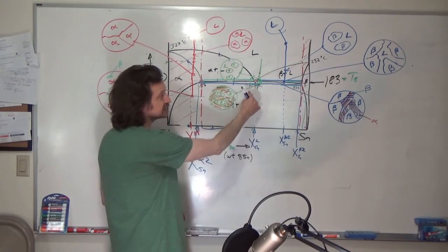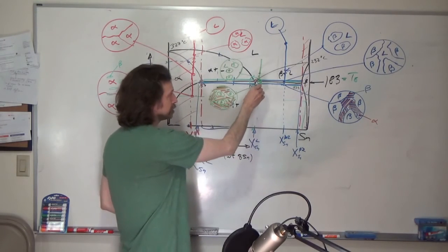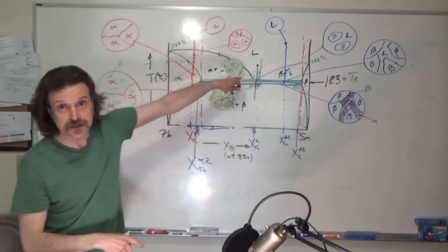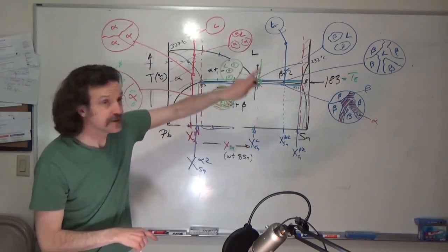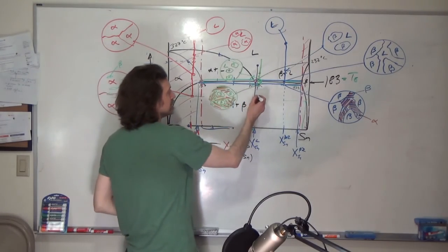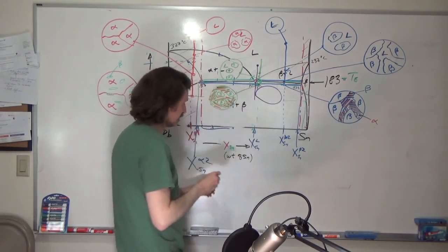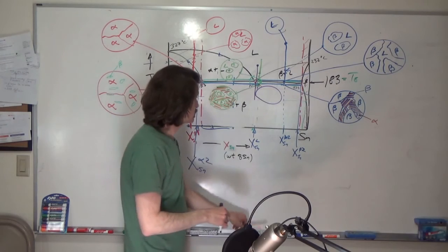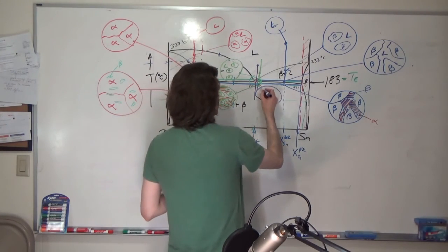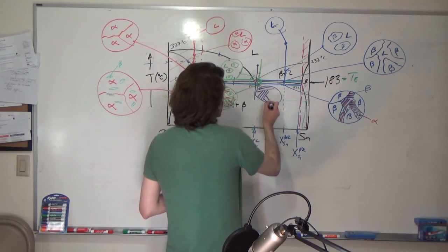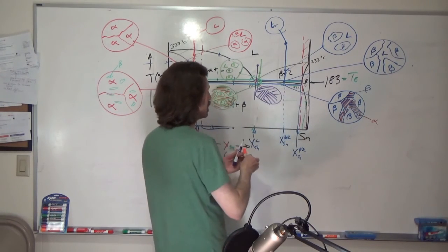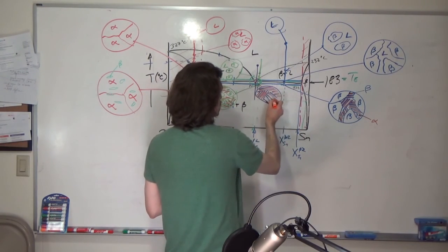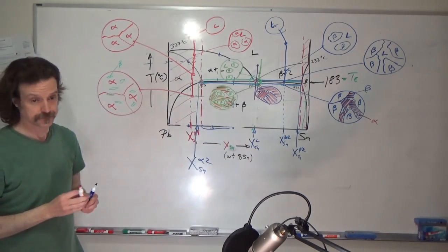And of course, if you pick a composition that is exactly at 61.9 and you cool down through the eutectic composition and eutectic temperature, well, in this region, you have pure eutectic microstructure. So you'll have no little beta crystals, but instead you'll have all this lathe pattern.